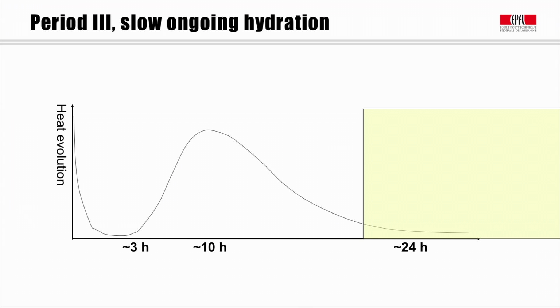But that's very deceptive, because at this point here of about 1 day, the degree of hydration would typically be about 50%, and the amount of strength would be maybe 20-25% of the final strength. So there's an awful lot going on in this later period beyond the first day. And in this module, we're going to try and look at what some of these things might be, although I have to tell you now that we still don't really know that much.